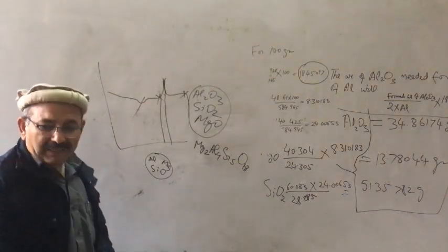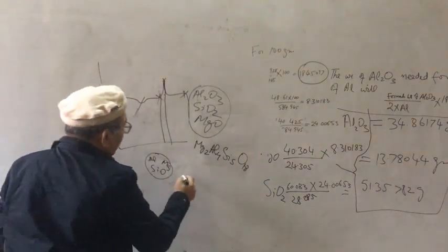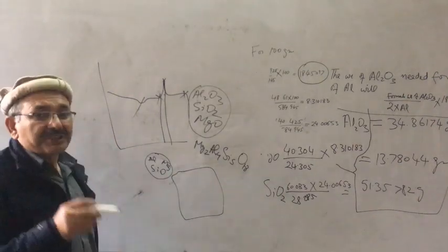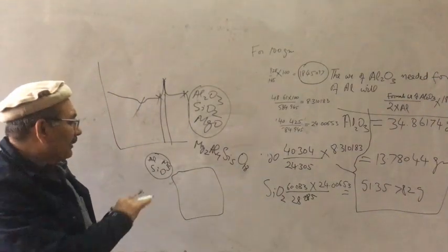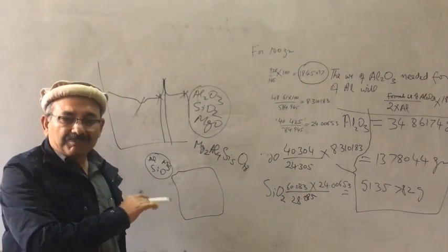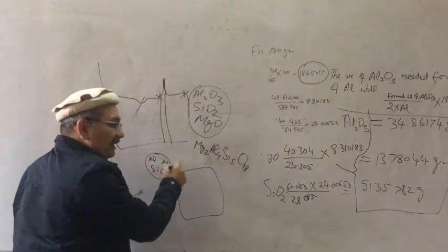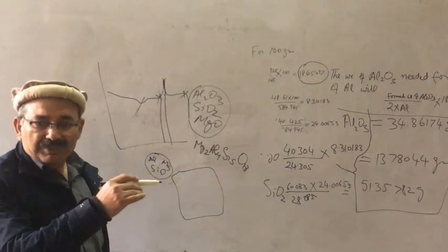Once you have known the calcination temperature, calcine the material in a furnace in the desired environment. If the material is highly reactive, people usually cover it with something. The temperature must be given properly, the heating rate must be given, and the soaking time must be given.